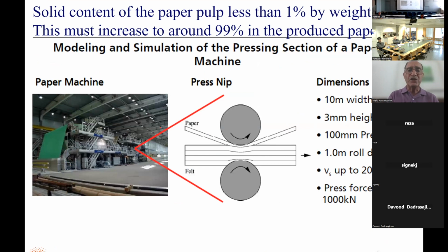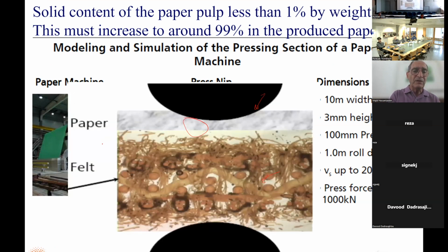This is done in the pressing section by moving the paper pulp that's shown here between two presses, two cylinders. And so the paper pulp that by now still has about 75% water by weight, they put it on a felt. This is a piece of clothy material, which is extremely hydrophilic and very dry. And by pressing this paper pulp, the moisture is basically pushed and sucked into this felt. And that reduces the amount of water to less than 10% by weight, and the rest has to be removed by drying. So this is another example of unsaturated flow.